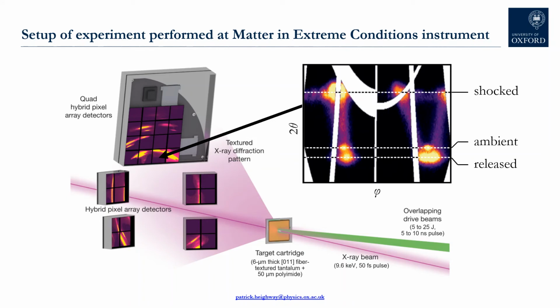Now, it so happens that the focusing of the X-ray beam provided by the beryllium lenses is somewhat imperfect, and we get what's called a halo around the XFEL beam proper, which falls outside the optical drive spot and thus always diffracts from uncompressed material. This gives rise to constant diffraction peaks whose position tells us the ambient density of the material. Conspicuously, the scattering angle of the released material is lower even than that of the ambient material. So that means the shock-released crystal is less dense than it was before it was shocked.